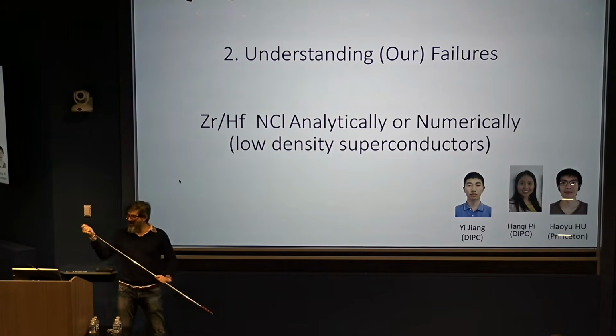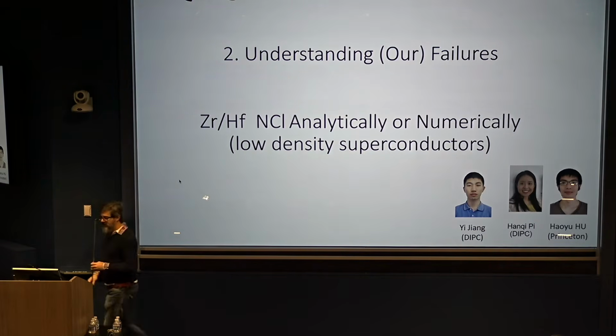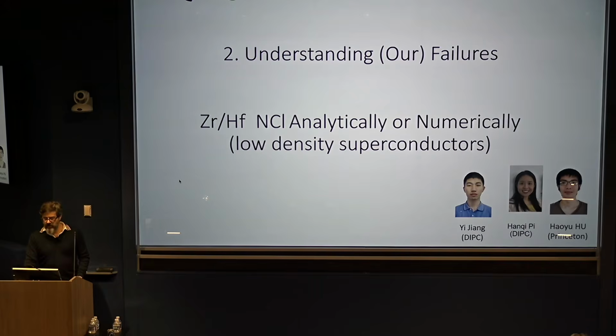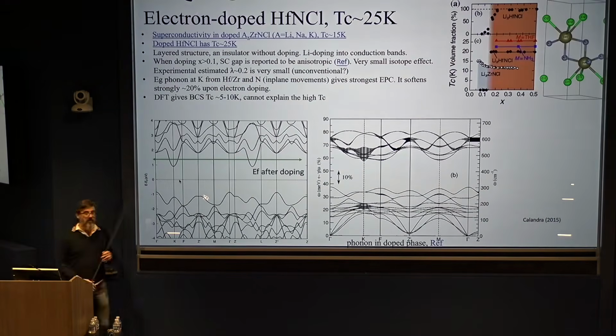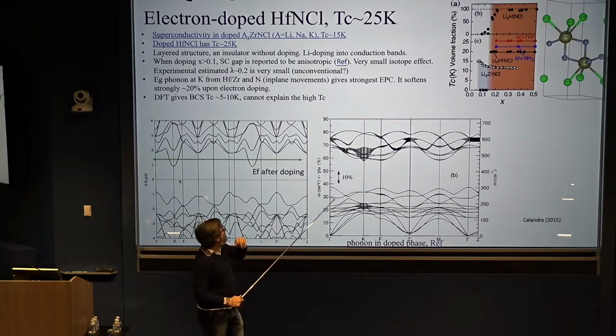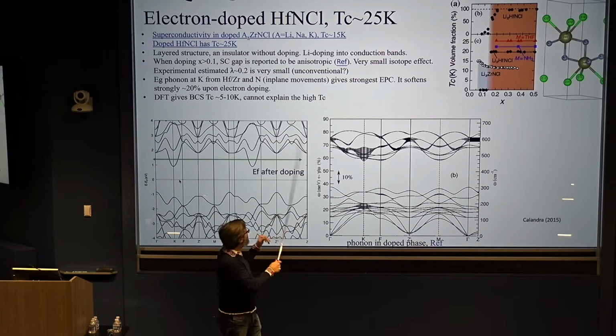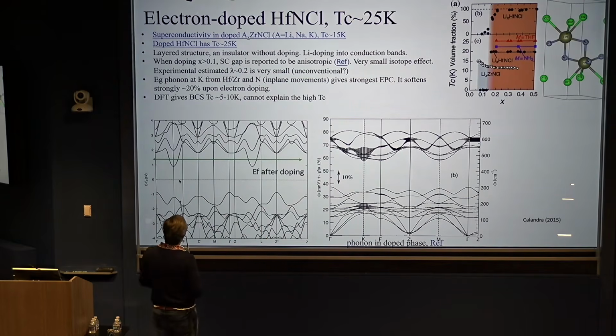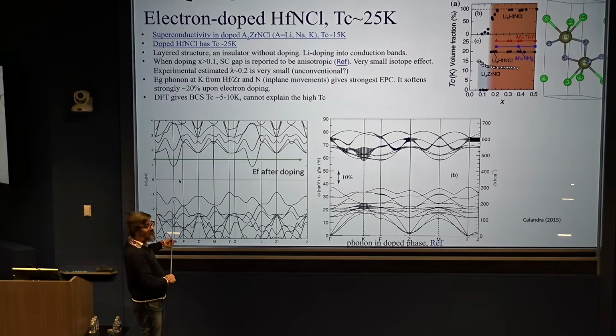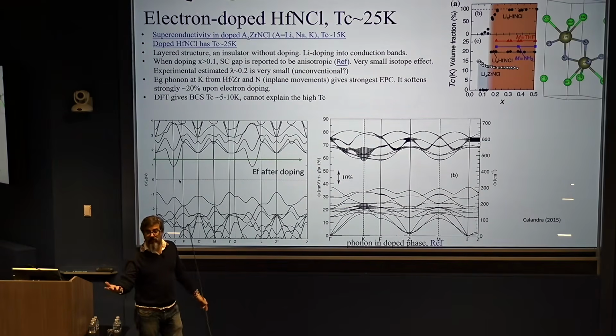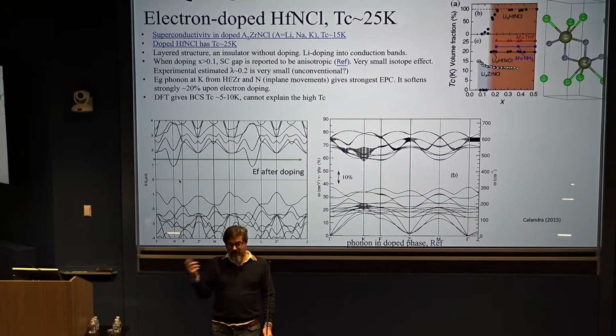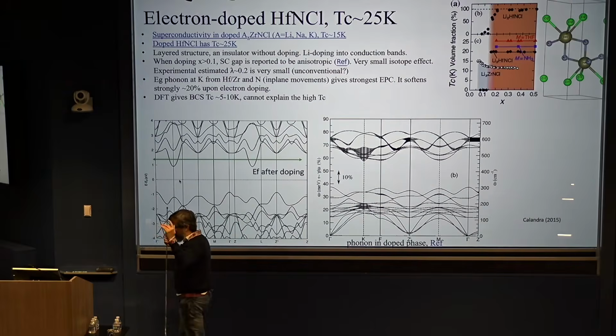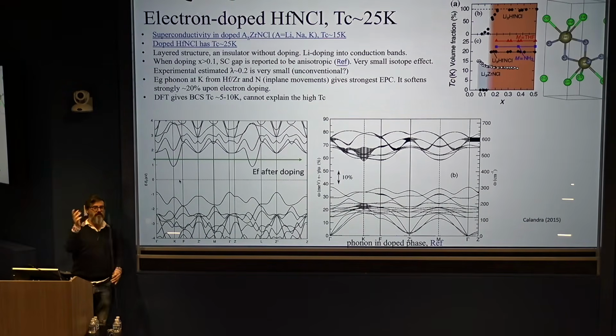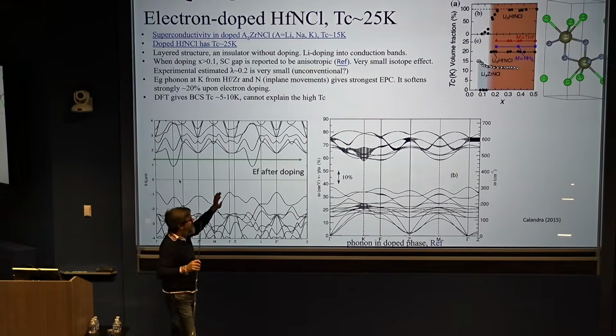Very good. Okay, so understanding failures. This is a failure for us. We couldn't understand it. It is basically hafnium or zirconium doped, lithium doped, this class of superconductors with rather high TC upon doping. It's a massive Dirac point here, and you dope it to about 100 milli-electron volts, and the omega of the phonon that's involved is about 70. So you're kind of in the regime that Oscar was talking about, EF smaller than omega, but again, it's good enough.